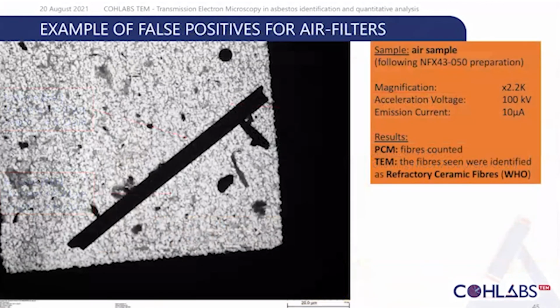Then there's another example of a filter. This one was analyzed by PCM, and this fiber was counted. But when we analyzed this using TEM, we found that it was not an asbestos fiber, but refractory ceramic fibers.